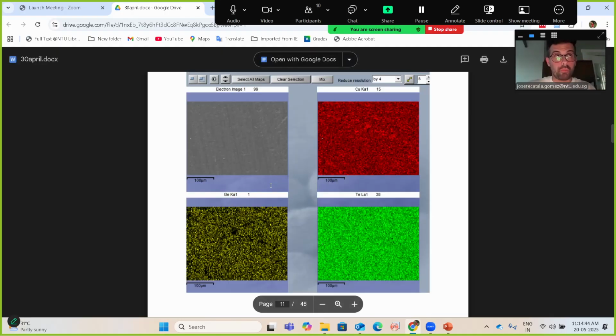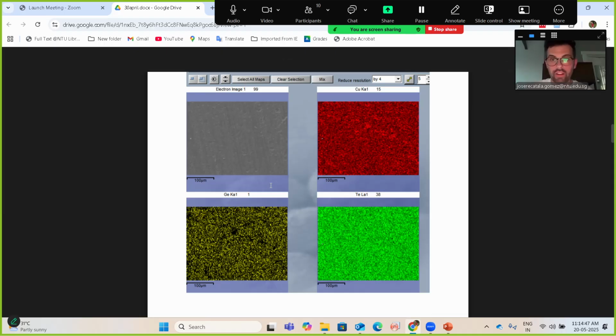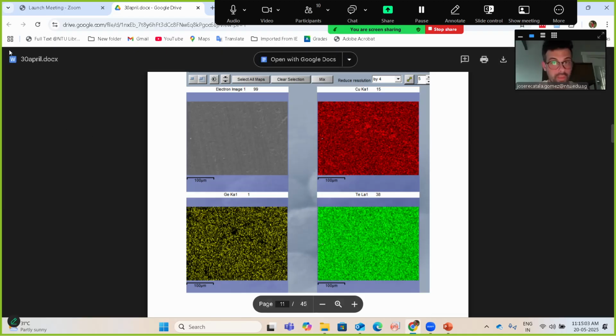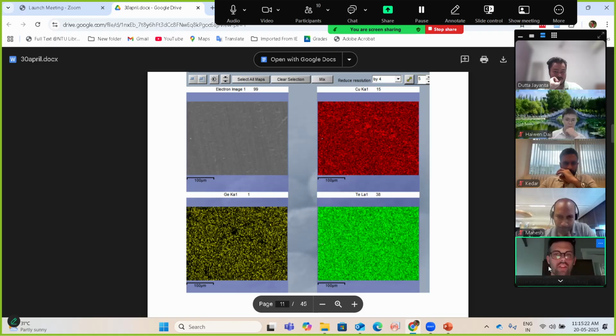It could even be that by pelletizing, you precipitate something, right? You could have a pure phase from the very beginning, but it could be possible. And even if you had the precipitates in the powder, you'd be fine. Your Rietveld refinement is very good. Honestly, all the peaks are fitted, the intensities are fine. In fact, a peak with the intensity not refined could be a telling sign that you have precipitates, because that intensity that you're missing is somewhere else. That's what intensity in XRD means. But either way, you're fine. That doesn't matter, frankly speaking.